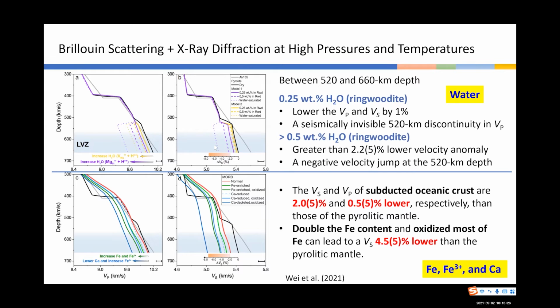Then we try to add water inside. Here we consider the influence of water on the velocity profile of the Earth's mantle in terms of the influence of the olivine polymorphs, because nowadays the effect of water on the elasticity of olivine polymorphs is much better experimentally constrained than for other mantle minerals. We can see the purple line and the yellow line are the same water-bearing model; the only difference is the water incorporation mechanism in ringwoodite. Here we just use the water content in ringwoodite to represent our hydrous model, and we also consider water partitioning between olivine, wadsleyite, and ringwoodite.